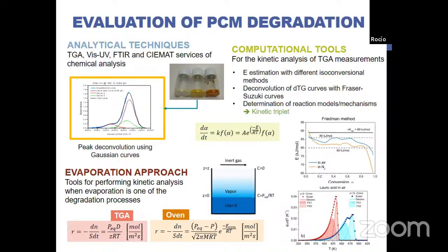We also have computational tools for the kinetic analysis of thermogravimetric measurements. With these tools, we can estimate the kinetic triplet, which is the activation energy, the pre-exponential factor, and the reaction mechanism of this degradation process. We can also do the deconvolution of TGA curves with Fraser-Suzuki curves. You have here a couple of examples of the results we can get. We have also developed an evaporation approach, because sometimes the degradation process of PCMs is evaporation. So we developed tools for performing the kinetic analysis when evaporation is one of these degradation processes, either for TGA measurements or for the oven results.